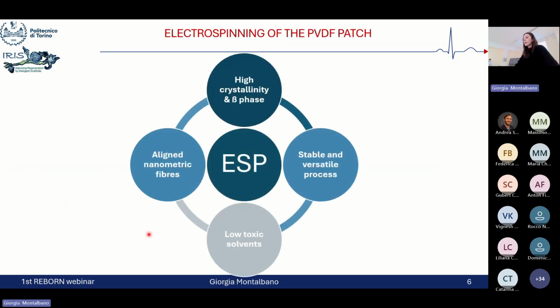So in Reborn, we have optimized and explored this very interesting and versatile processing technique, mainly to address some key aspects: not only the improvement of the manufacturing process in terms of stability and versatility of the overall electrospinning process, but also toward the use of lower toxic solvents compared to the gold standard for electrospinning. But also with a view to improve the piezoelectricity of our materials, so in order to control the crystallinity content and increase the electroactive phase, and also to induce the alignment of the deposited fibers in order to obtain more